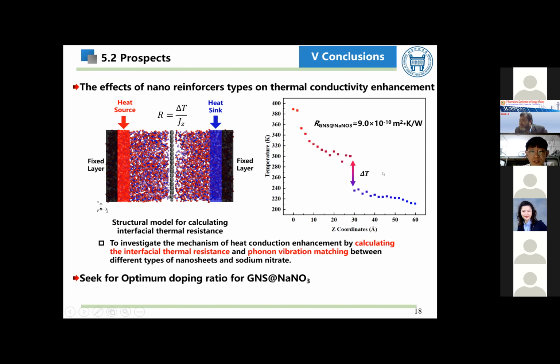The simulation results of the interfacial thermal resistance between GNS and sodium nitrate are shown in the figure. The interfacial thermal resistance between boron nitride nanosheets and sodium nitrate would be our next step. Besides, the phase change properties and the thermal conductivity of different mass doping ratios would be calculated to seek the best one.